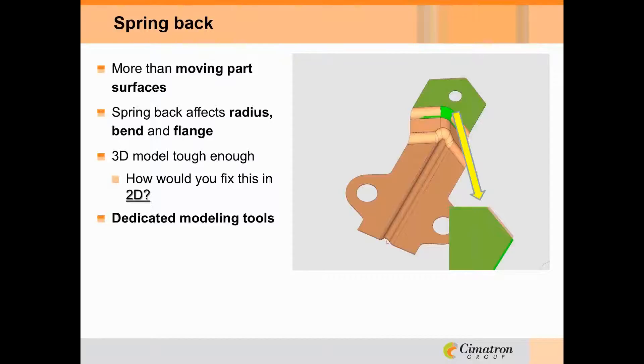Adjusting a part to accommodate springback is more than just moving surfaces around. That green face needs to be tipped down to deal with 18 thousandths of springback, but it's going to affect the entire radius at that point. Even in a very simple part, there's work needed to model and correct it. You may choose to model it on the part or on the die steel surfaces in your CAD design. And if you're working from a 2D print, it's important to keep those prints current with the design level — otherwise you're fated to go through the same hassles again.